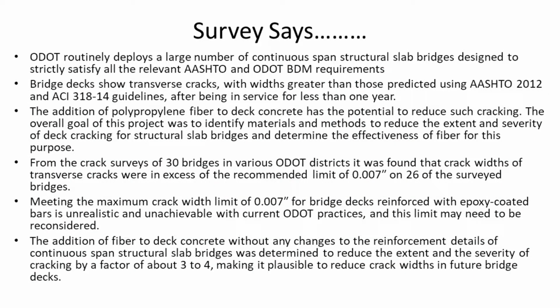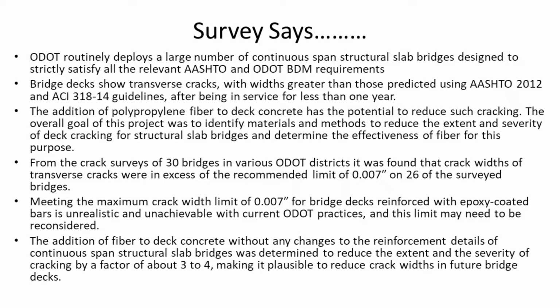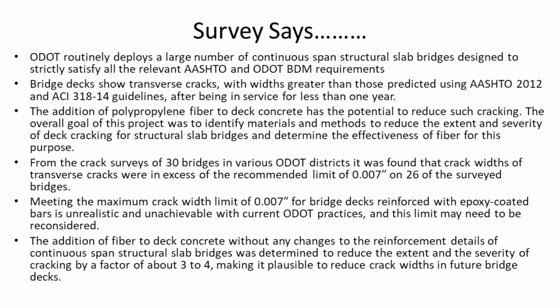From the crack surveys of 30 bridges they picked, and they had actually over 90 available that they could do, they limited it to 30 in the different districts and found that 26 of them had more than the recommended crack width of 0.007, 26 of the 30 in that first year. And they also found that the maximum crack width of 0.007 for bridge decks with epoxy coated bars was probably unrealistic for the goals they had set out. So change the bar a little bit, but change the practices as well, because they still want to use epoxy and look at alternatives for that.